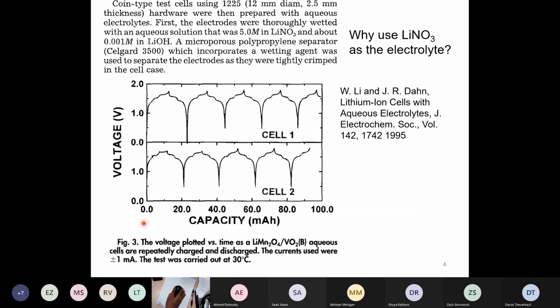These are some data from that paper in the Journal of the Electrochemical Society, showing charging and discharging of about a 1.5 volt system, with 2 cells doing the same type of thing. When you read this, it says that we used a 5 molar lithium nitrate electrolyte and then a little bit of lithium hydroxide to adjust the pH. We wanted to use lithium nitrate as the electrolyte to get something close to neutral pH for the reasons I talked about on the previous slide. These cells worked okay, and like most people promoting some new battery technology, you only show the first few cycles, in case everything becomes crappy afterwards.